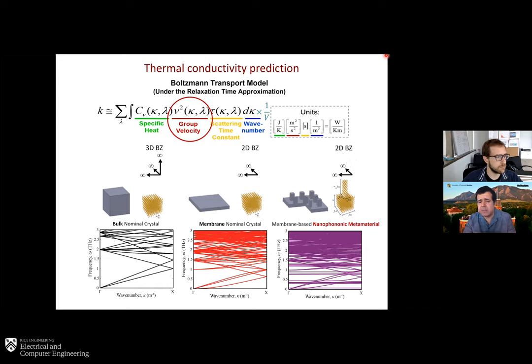Each atom in that pillar has 3 degrees of freedom, and for each degree of freedom, you have a mode. So imagine having a pillar on the order of, let's say, 20 by 20 or 40 by 40 nanometers in the base, and then maybe 500 nanometers in height. We're already talking millions, if not tens of millions, of resonances. All of these resonances play a role, and that's what's unique about this nanostructure.